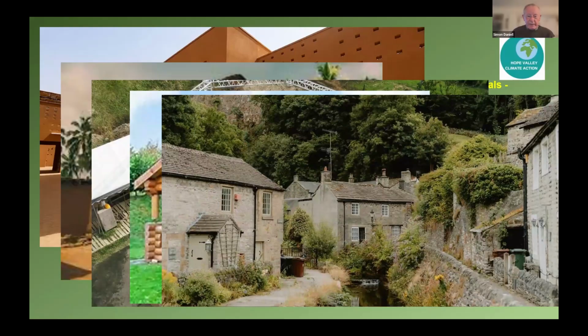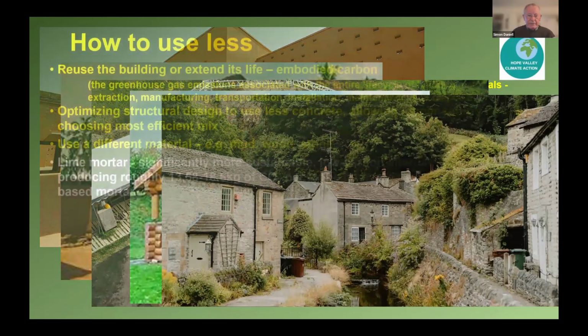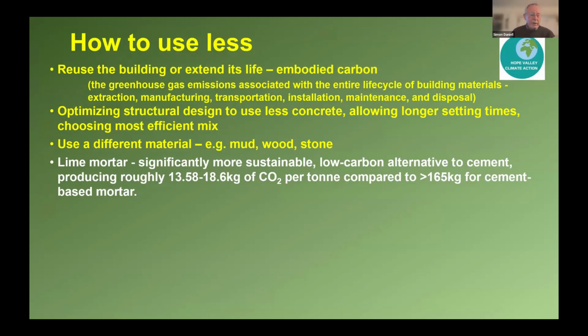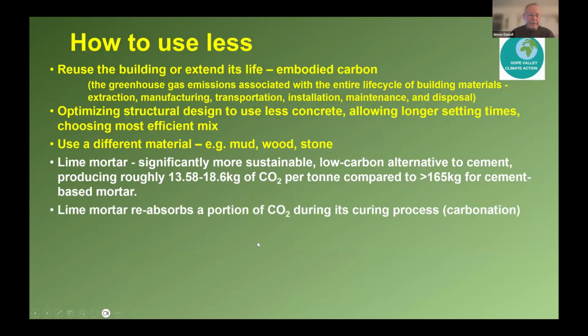And this is Castleton. Here we are with a lot of stone on the buildings, another way of reducing it. And in fact, with our traditional buildings here in the Peak District, we put them together with lime mortar. And that actually is very much more low carbon than using a cement-based mortar. And the other advantage of lime mortar is as it cures, it actually captures CO2, and this is called carbonation.